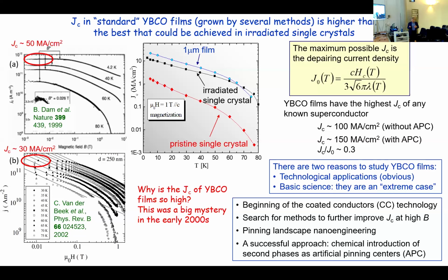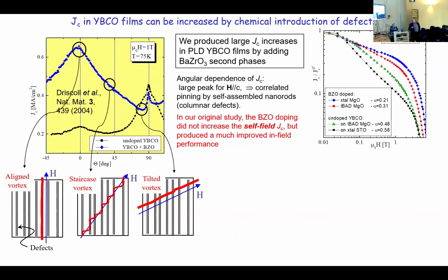So that was the beginning of the coated conductor technology and the search for methods to further improve JC at high fields and to start what is called vortex pinning nanoengineering. And the most successful approach was the chemical introduction of second phases. This is pioneer work that we did, led by Judith Driscoll when she was at sabbatical at Los Alamos, introducing barium zirconate that forms nanorods by self-assembly.